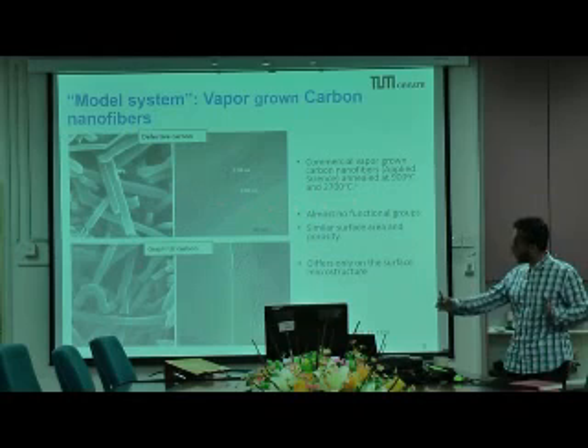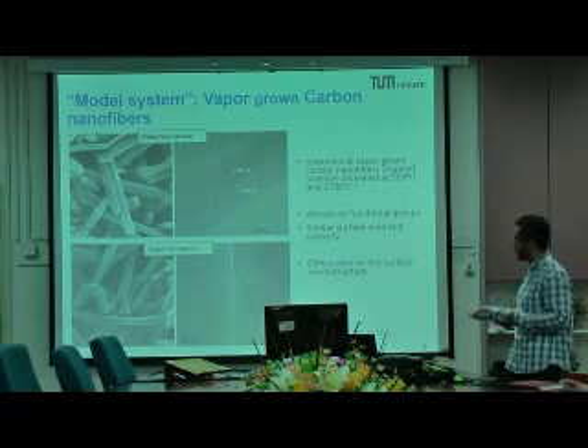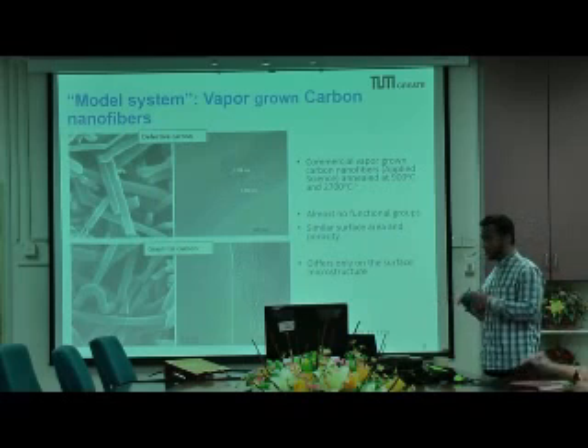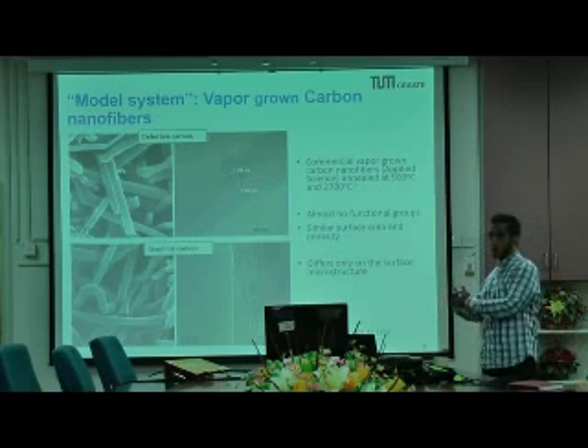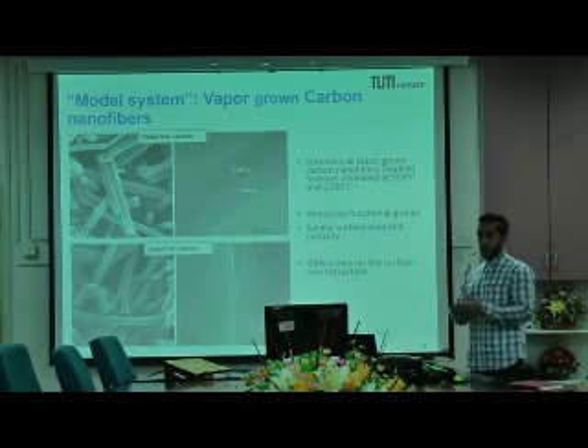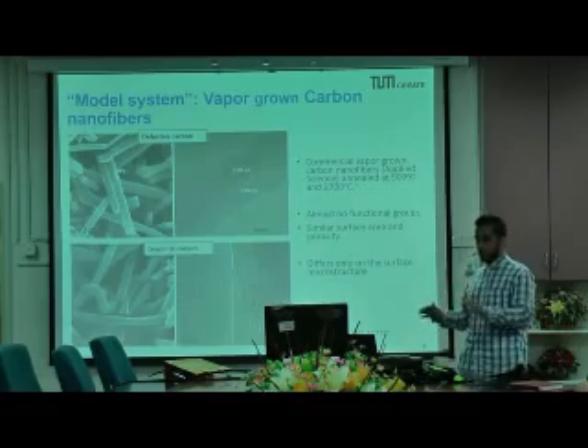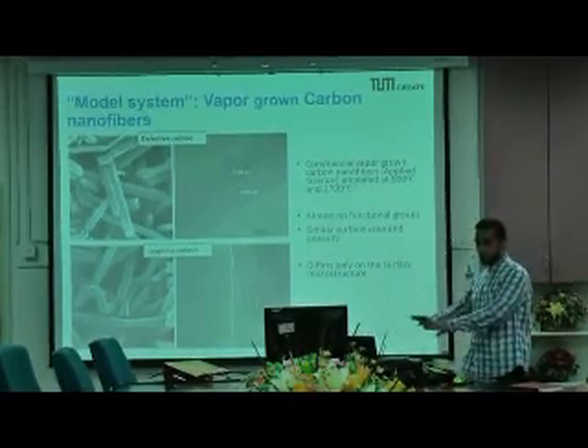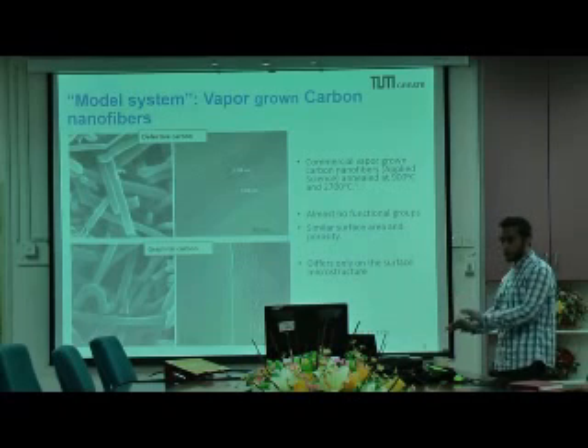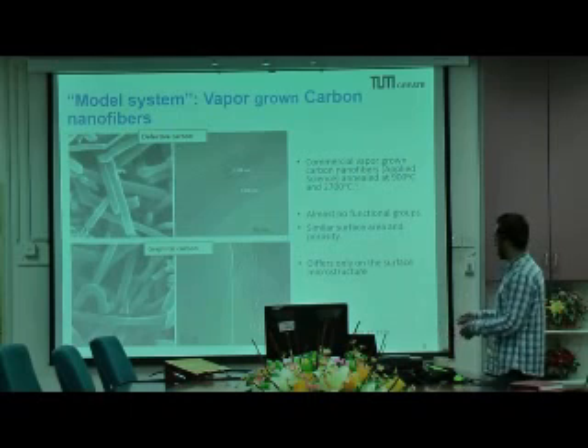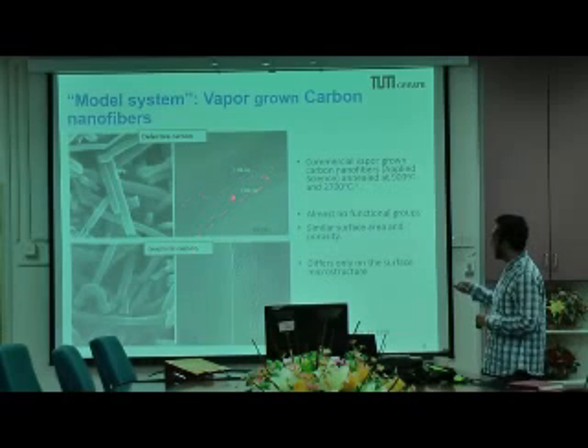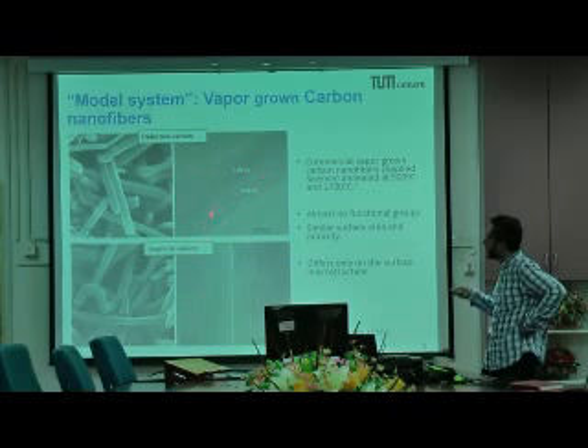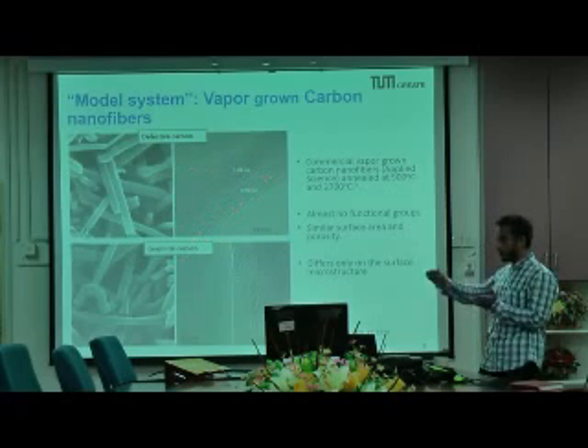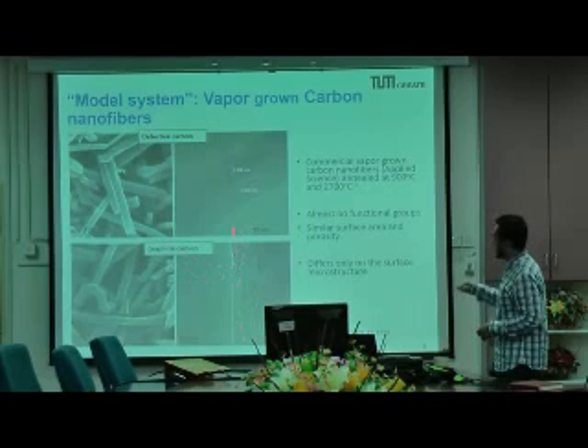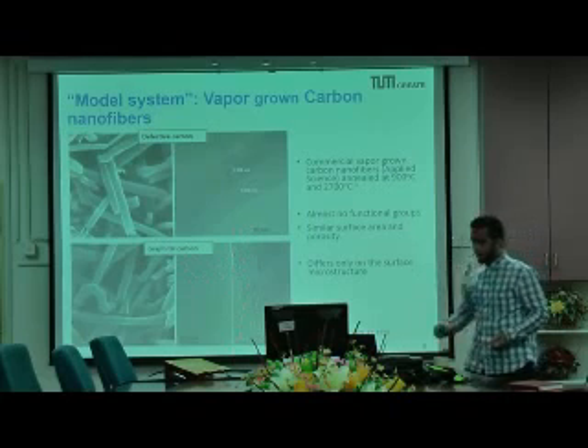So they have a range of vapor-grown fibers synthesized in the same manner, but at a different temperature. So in terms of functional groups, they are both very minimal, so you can neglect the effect of functional groups. And in terms of surface area and pore structure, they are the same. Actually, the same material, just at a different temperature. So you don't have the complicated problems that can interfere with the interpretation of results coming from surface area, porosity and so on. So in this case, the only variation mostly comes from the different surface structure that they have. The defective carbon has a very defective structure, as you can see here, where the ridge length is quite short, and the graphitic carbon is, as you see, a very nice straight line of graphene layers.